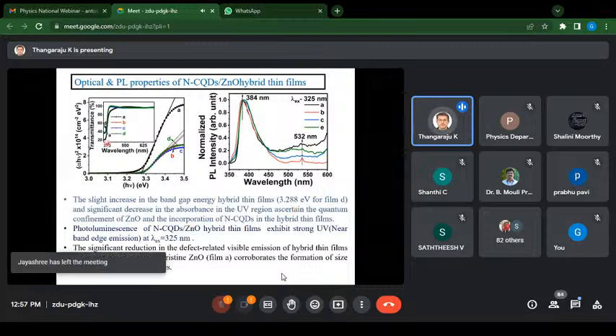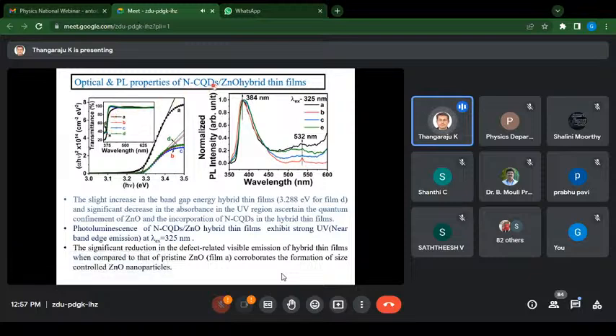So you can also see that the transparency of the carbon quantum dots based zinc oxide hybrid thin film is above 90%, close to 100%. Even after incorporating the carbon quantum dots, the transparency of the film is maintained at the high level of 96%.